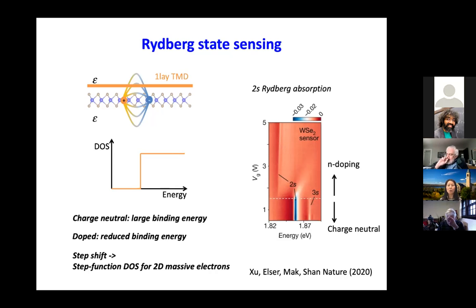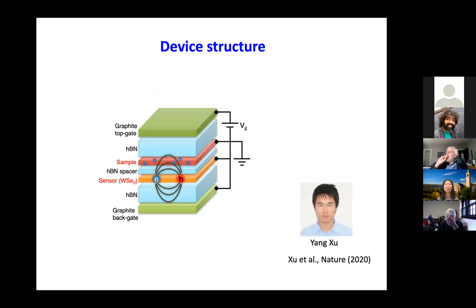So now we come in with the real experiment. I have my sample. In this case, it will be these Moiré layers, the electrons sitting in those periodic traps with a period of about 10 nanometers. I will try to load the electrons into those traps, 1 per 3, 1 per 4, whatever. And then I put this sensor layer very close to it, about 1 nanometer away.